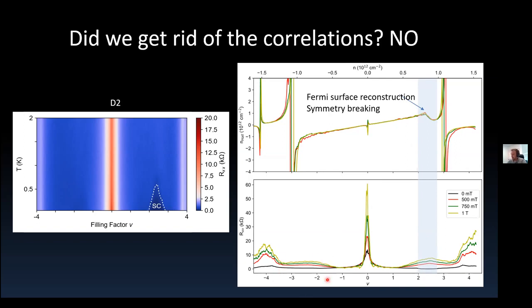The other thing that I want to point out is that if you go on the hole side, you see a very similar type of increase in resistance, but in this region there is no change of the hole conductance, and there's no superconductivity. So this can tell you that this reconstruction is a needed ingredient for establishing superconductivity. But it also tells you that if you want to get rid of all correlations just by using screening, it's going to be really hard, because if you're at the magic angle and you want to screen your interactions, you are going to need unreasonably thin hBNs.